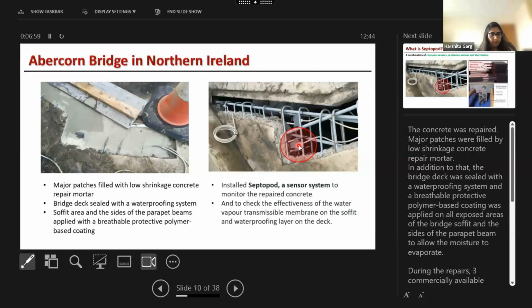So therefore, the bridge was repaired and the major patches were filled with low shrinkage concrete repair mortar. Along with that, the bridge deck was sealed with a waterproofing layer, while the soffit area and the sides of the parapet beams were coated with a breathable protective polymer-based coating so that it allows the moisture to evaporate. In addition to that, during the repairs, 3 commercially available sensors called septopods, as seen here, were installed. The aim behind installing these sensors was to check the effectiveness of the water vapor transmissible membrane on the soffit and the waterproofing layer on the deck surface. Also to see the rate of chloride ingress in the concrete.